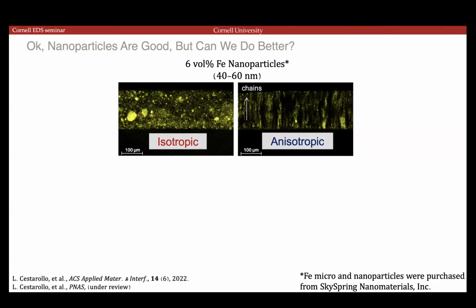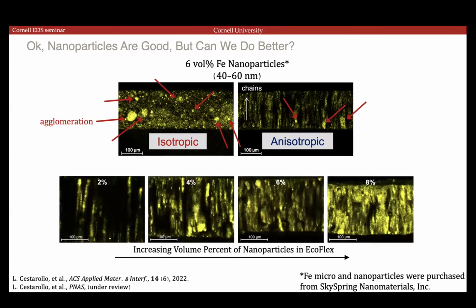The magnetic particles need to be coupled so that one is applying a field on the other, and then overall we get a higher remnant magnetization. But when you look at these films, it's not perfect chaining. It does look like there's agglomeration in certain regions, whereas the ideal case would be one particle wide chains. It's not the case. So if you start looking at where those agglomerations are, you'll easily start to find fault in these films very quickly.